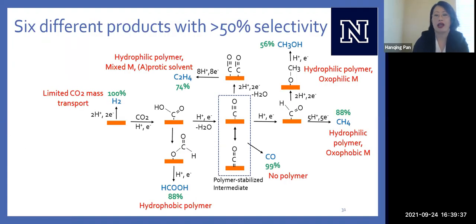So we can summarize everything into a mechanism, and I won't go into detail about this today, but the idea is that I'm able to generate these 6 different products with over 50% selectivity. So again, under properly controlled conditions, we can control hydrophobicity, we can control our solvent, we can control the metal, we can control the polymer, we can control the thickness of the polymer. And so under these properly controlled conditions, we can control product selectivity.